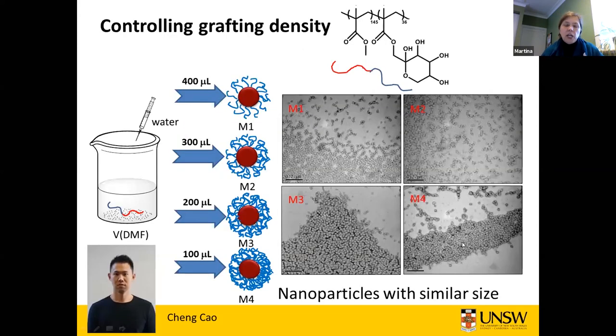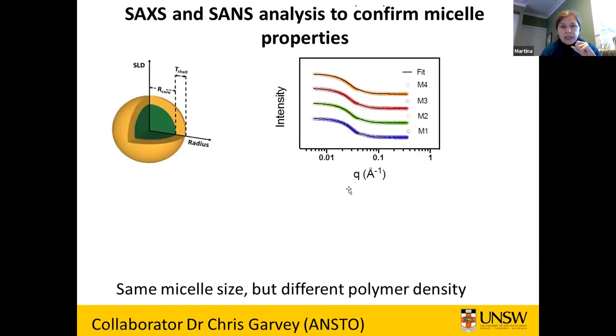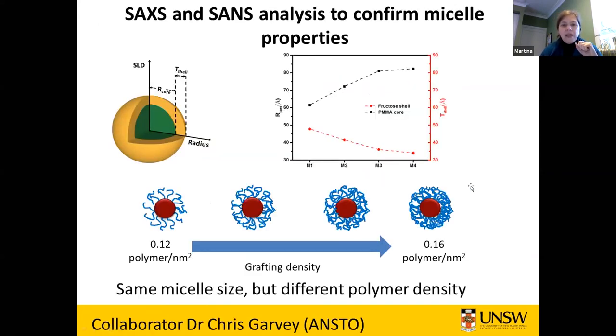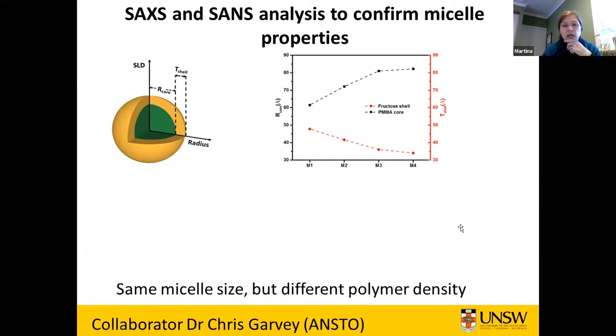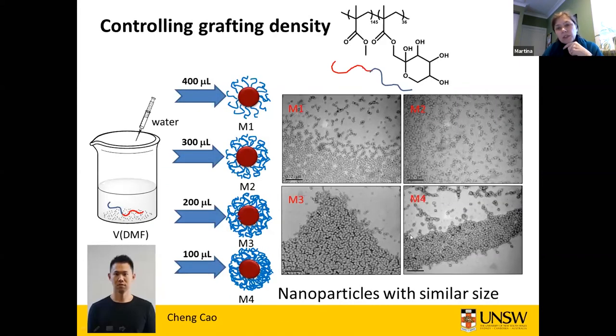So we can do that by changing the conditions in which we make these nanoparticles. And what the student Cheng did here, he played around a little bit with how we made these nanoparticles. And he got four types of nanoparticles. And they all looked like they had the same size. But what we knew now from scattering techniques is that they had different grafting densities. So when we go back here, although they looked the same under the microscope, the reality was they had very different grafting densities. So M4 here had very, very dense polymers, M1 had very loose polymers.